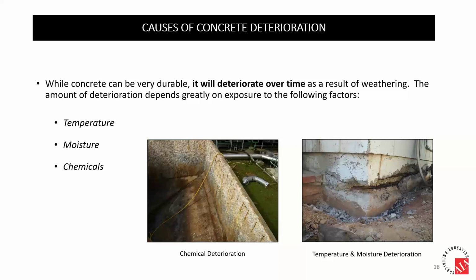The left picture is a water tank, and you can see the rebar is highly corroded and rusted. That's a chemical reaction. And the picture to the right is an example of spalling, where concrete cracks from the inside out, and you can now clearly see the steel structure is completely rusted and deteriorating.